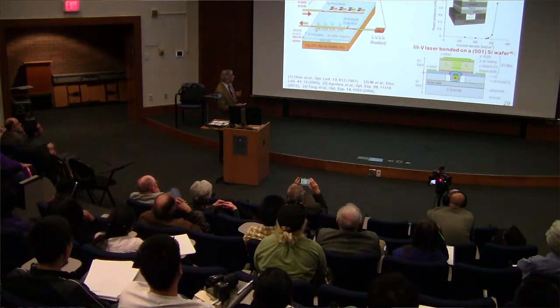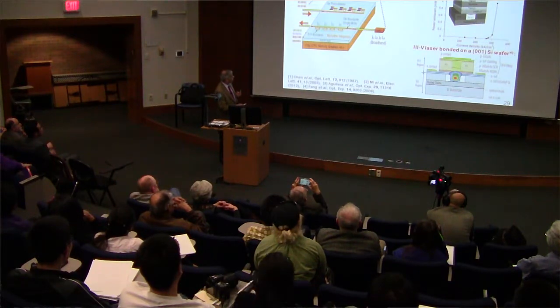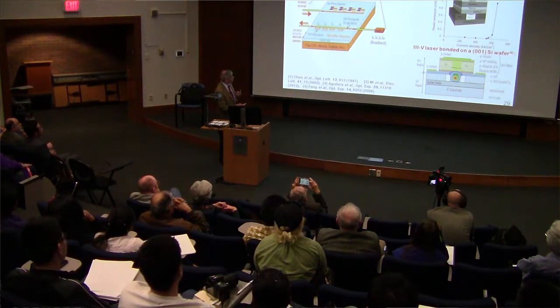We demonstrated better lasers with indium arsenide quantum dots on silicon. The problem with this is that you cannot grow gallium arsenide on silicon. One is polar, the other one is nonpolar, so you develop antiphase domains, and you just can't do it. So what we do is we have to tilt the substrate, and of course the CMOS industry is not going to build anything on tilted substrates.